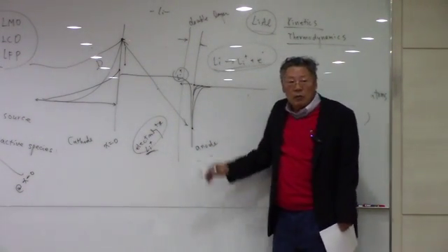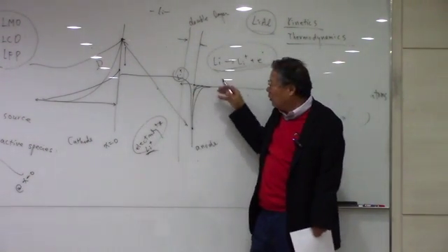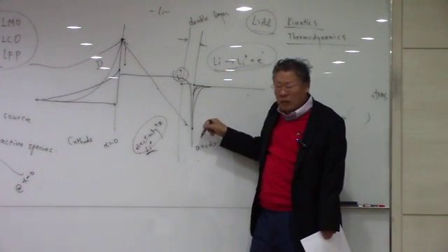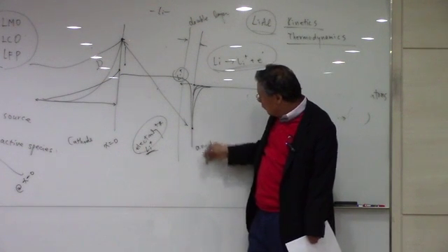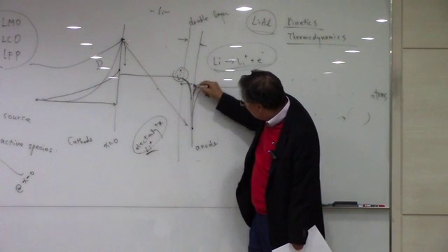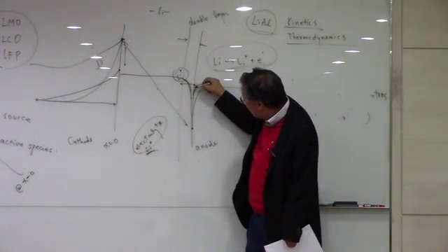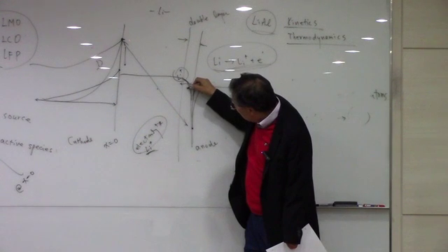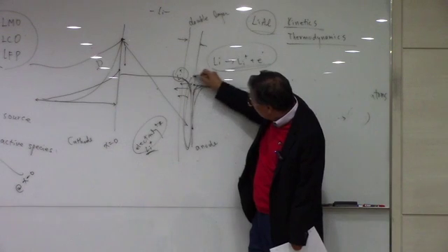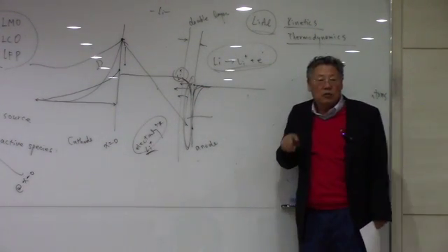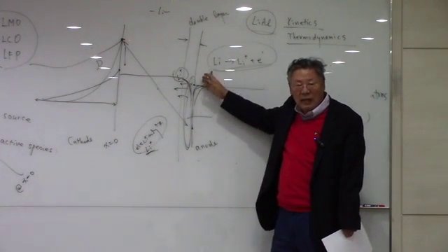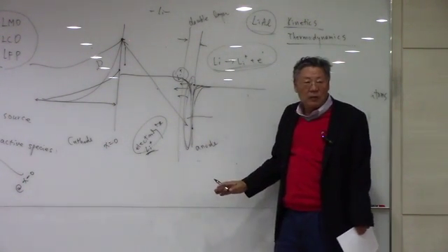Okay, the resistance is so high that all the potential is concentrated in the vicinity, very close to the anode surface, so that the lithium ion is going to be supplied, and it's going to form some depleted zone, a depleted region of lithium ions at the surface of the anode.